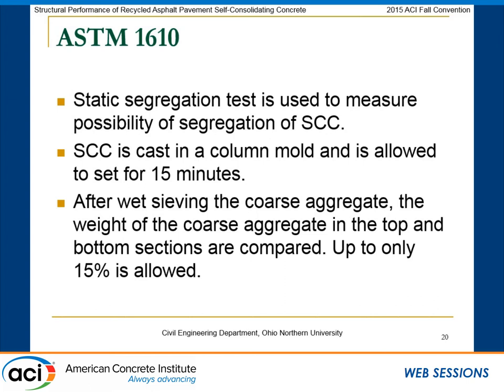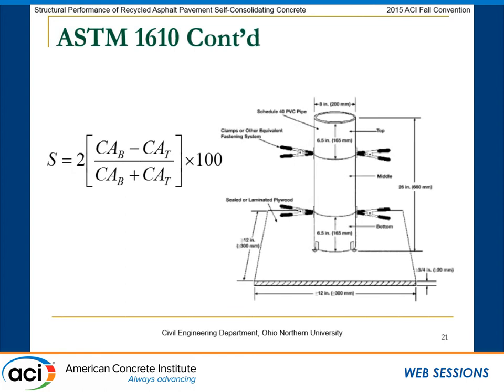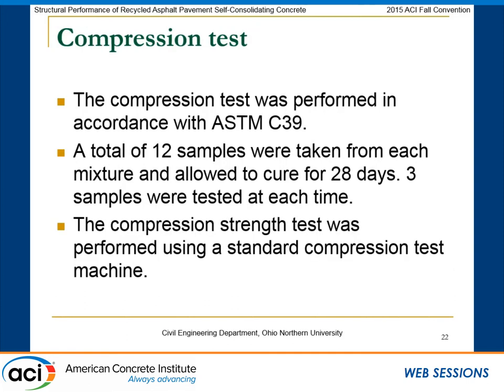Then you wash out the coarse aggregates and weigh the coarse aggregate in the top section and also in the bottom section. If the difference between the two weights is less than 15%, then you don't have significant segregation in your mix, and that would be acceptable. This is a schematic of the column, and this is the equation that can be used to calculate the segregation percentage.